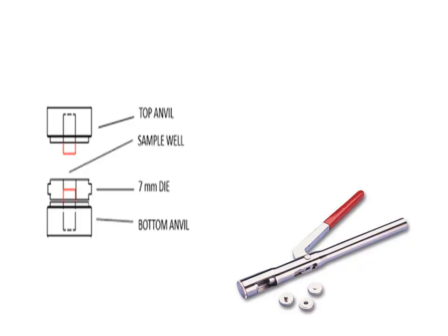Now this is the way. It's a simple technique. As you prepare your tablets, you have a 7 millimeter die, and you get a very fine crystalline wafer. You have a bottom anvil and a top anvil like your punches. You just apply a very high pressure of 10,000 to 15,000 psi and you will get your wafer.